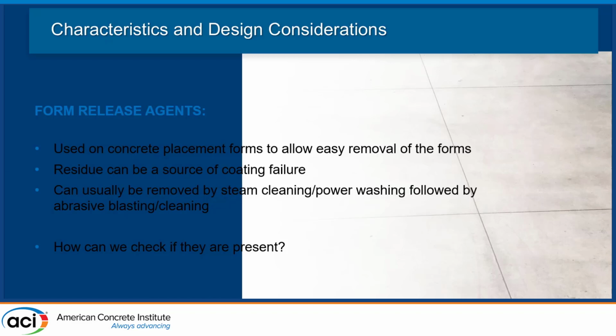And then a way that you can actually check for that is the water break test. If you put a drop of water on a piece of concrete, if it beads up and runs off, there's probably a surface contaminant there. We want porous concrete for our coatings to adhere to.